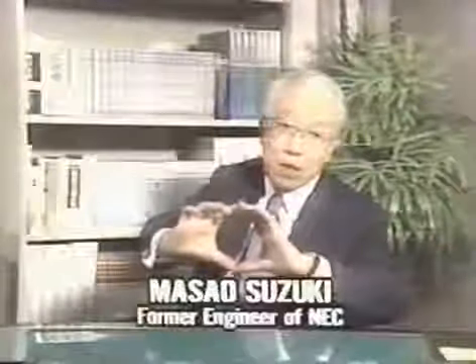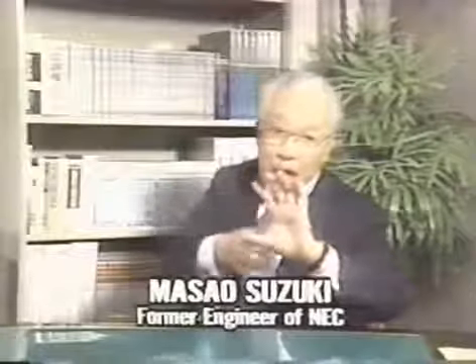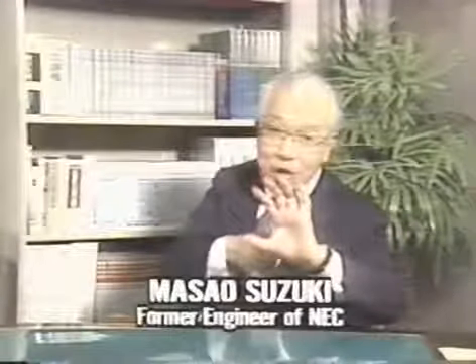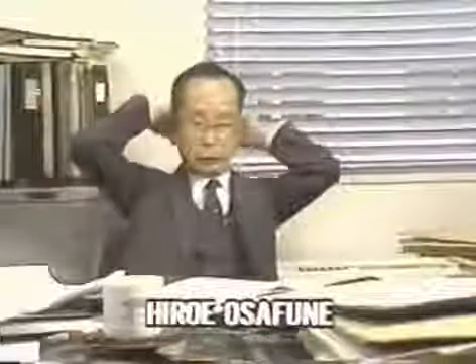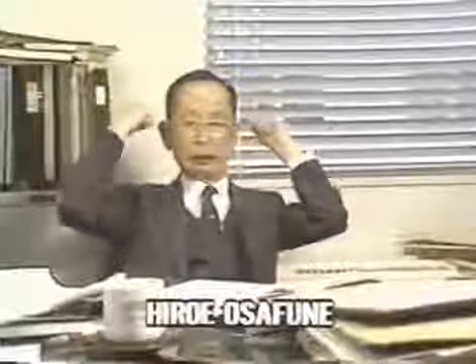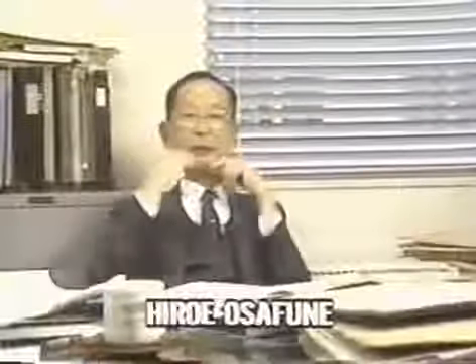All they had to do was increase the revolutions per minute to about 3,300. But Mr. Osafune is a rough sort, and since he's not a machinist, he just thought all he had to do was spin the cutter and slice. Because he paid no attention or concern whatsoever to something like the number of revolutions per minute, it broke apart and flew into pieces. Bam!